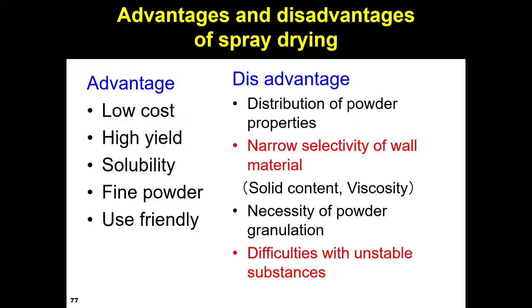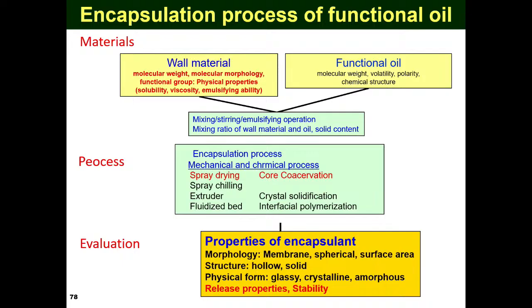The advantage of spray drying is low cost in the food industry. Many companies use the spray dryer because the process cost is low. High yield, solubility, fine powder, user friendly. But the disadvantage is the narrow selectivity of wall material. So we have to select high glass transition temperature materials. And then there are difficulties with unstable substances. So, the process for a functional oil case: wall material, functional oil. The wall material includes the emulsifier.